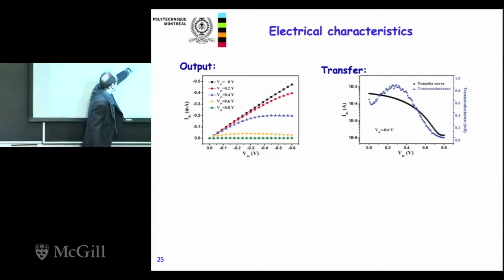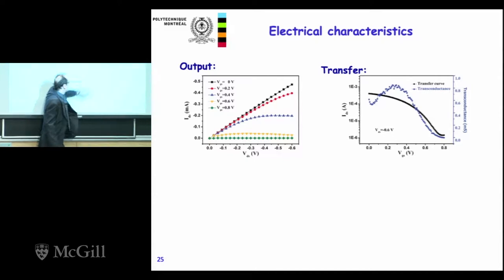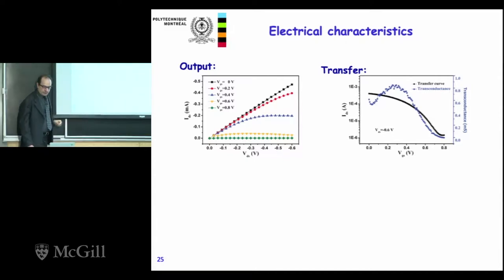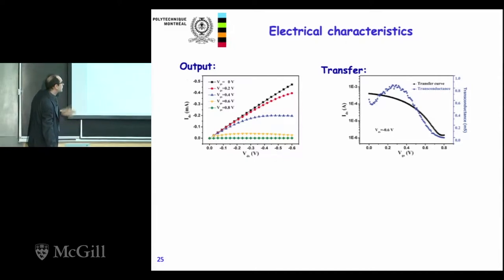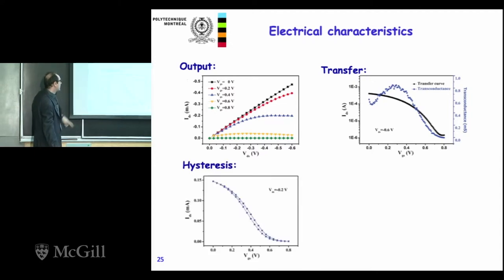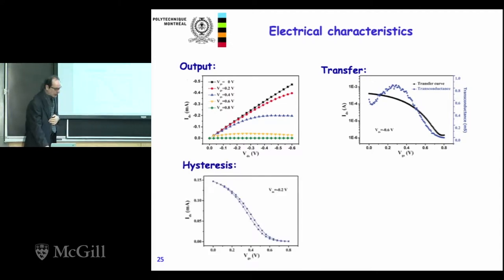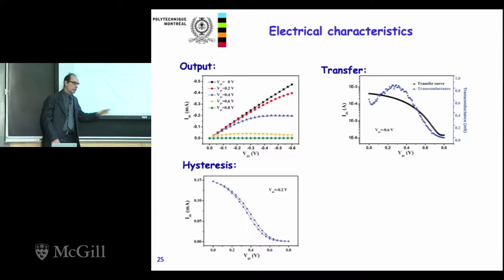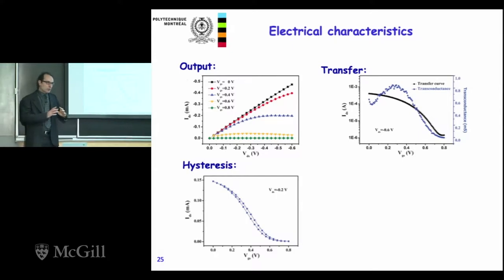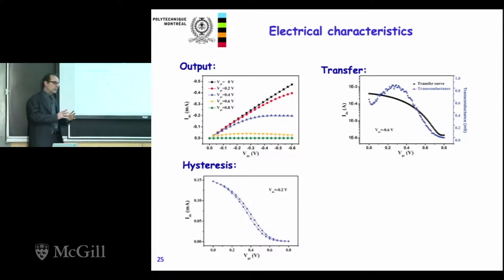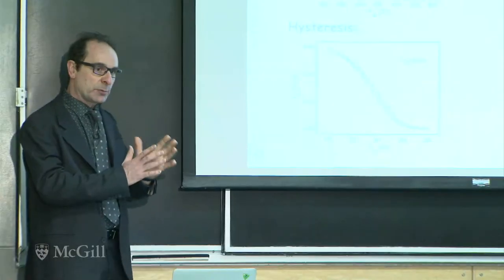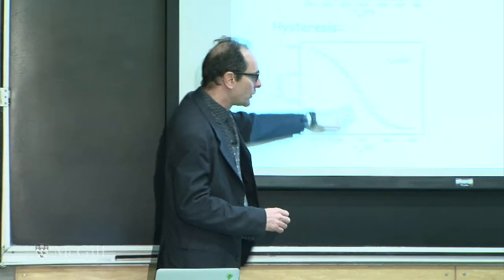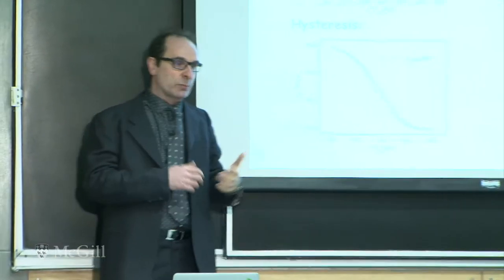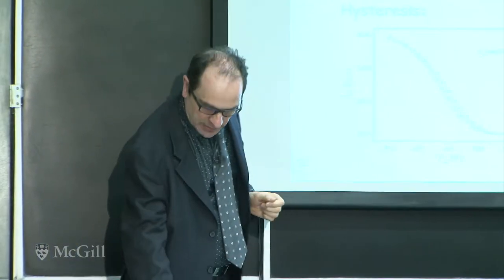See the same thing here. This is again current versus the gate voltage at fixed drain voltage. You see good switching characteristics. Low hysteresis, which is very important. You can achieve this only if you make your channel very small. So if you don't have too much material and if you have a very small gap between source and drain, otherwise your ion movement is slower compared to the movement of the electrons, and this results in high hysteresis.